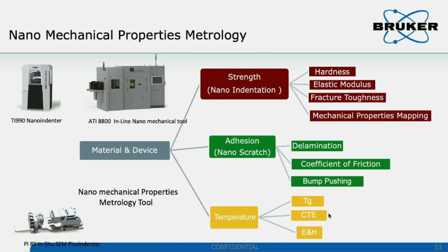to micro to millimeter. And we have nanotribology to help us to understand thin film adhesion, coefficient of friction, and also in semicon we have some structure testing for the bump. At temperature, we can measure the CTE, Tg, and also the mechanical properties across the different temperatures. So this is my first presentation today, and hopefully this helps you to have more idea about the most advanced nanotechnology for the mechanical properties measurement.